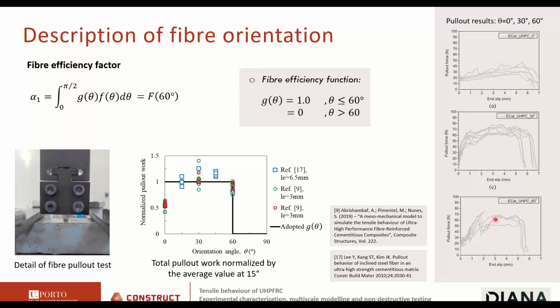So what do we know? For a slip of 3 millimeters, in the real UHPFRC specimen, the crack is already localized. So we have already gone through the peak. We are already in the softening regime of the tensile curve. So although they can develop force, the force is not developed where you need it, which would be here for very small slips.